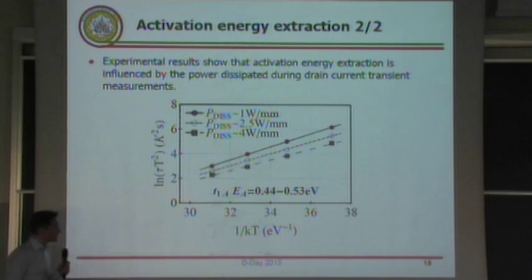However, the problem we found is that the activation energy measurement is affected by the dissipated power, because during the measurement we have the device on, we are measuring the drain current, so the device is on with a non-zero VDS. In these devices, since we have extremely high current density, it's easy to obtain very high power densities, as you can see here, even if low VDS voltages are used. And as can be seen in this graph, we have three different Arrhenius plots that depend on the dissipated power during the measurement, and we extracted three different values of the activation energy. So from this measurement, I cannot state which is the real activation energy of the defect.